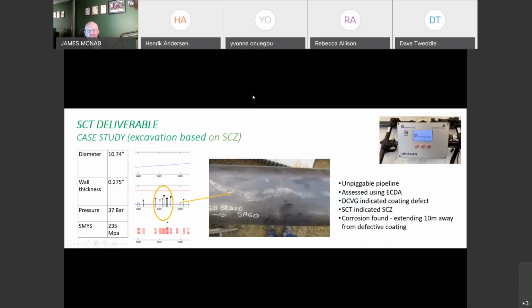During the excavation, you can see in the photograph there, we found deep corrosion at the 12 o'clock position along the pipe, but interestingly, the corrosion actually spread. If you can see in that graph that I pointed to on the left-hand side with the bars and squares on top, a number of stress concentration zones longitudinally along the pipe. This particular area of corrosion extended 10 meters past the defective coating area. So really, this is just to give you an idea of one of the previous successes on which we're basing this adaptation of the technology.